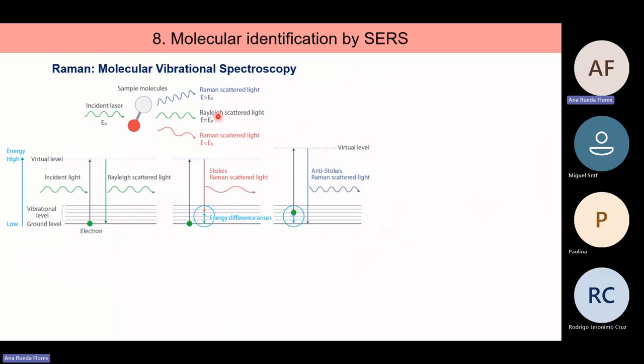So in a Raman spectrum, we illuminate with coherent light. The majority of the light goes through without suffering any scattering, but a small amount of the light, less than 1 part per billion, suffers a scattering with these vibrational states. So for instance, you can start with a ground state, with the light you go to the virtual level, and when it decays, you can decay to a higher energy level. So the scattered light has lower energy than the light we were using for the illumination.